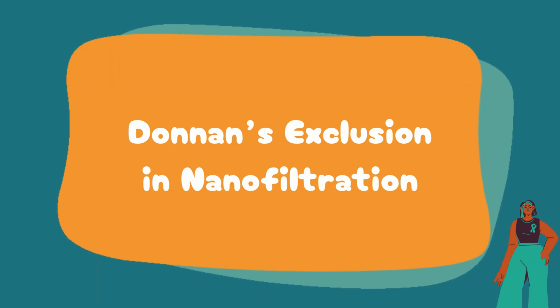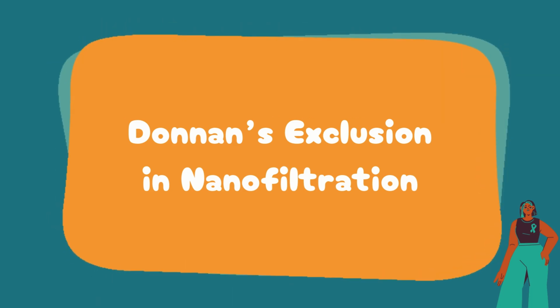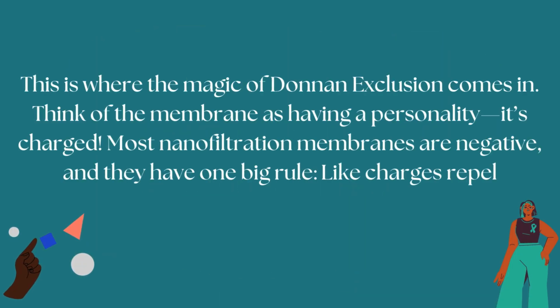Nanofiltration membranes usually have a slight negative charge because of functional groups like carboxyl or sulfonic acids on their surface. This charge creates an electrostatic barrier that repels similarly charged ions like sulfates and phosphates. Wait, so it's not just a physical filter, it's got personality too?